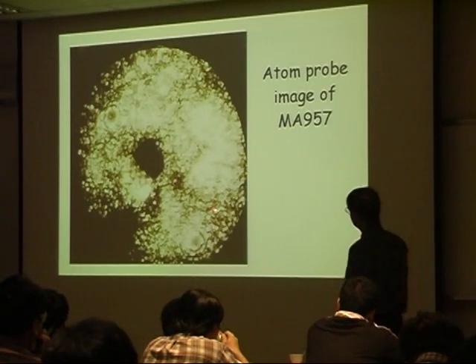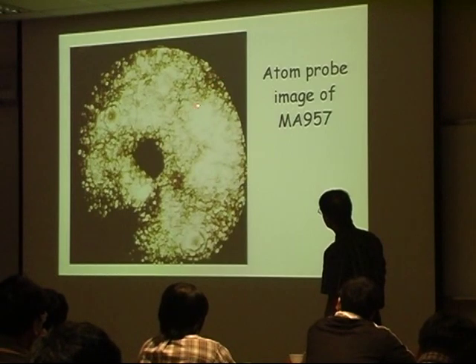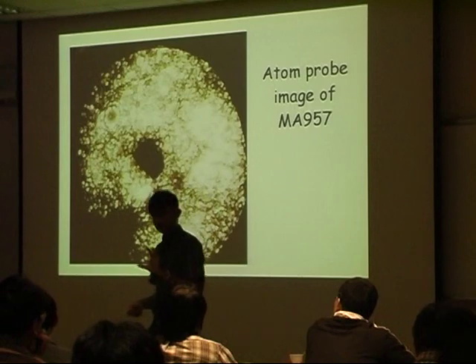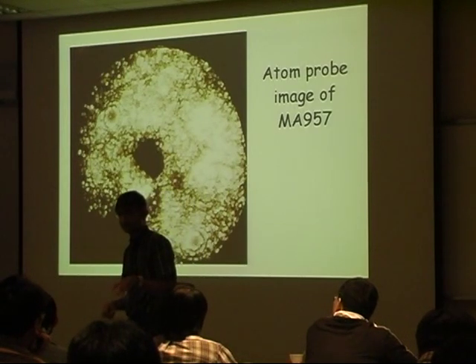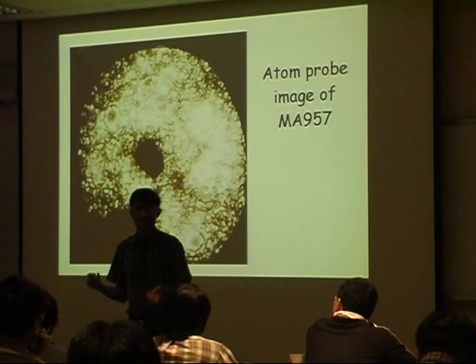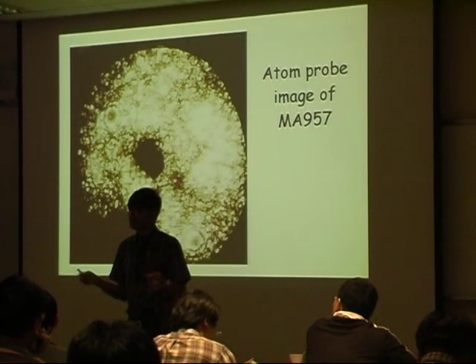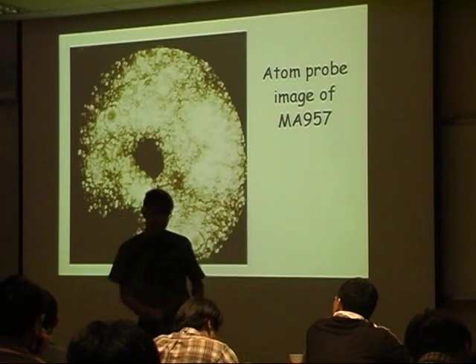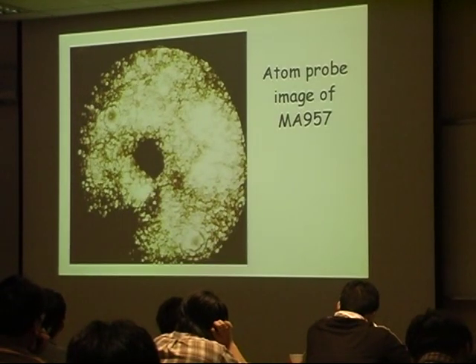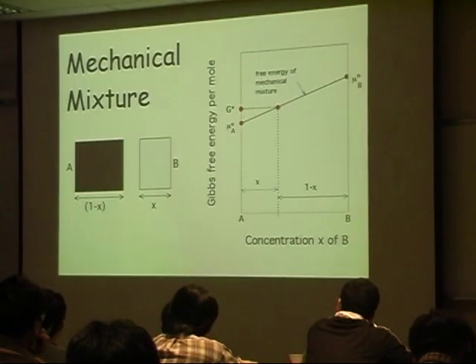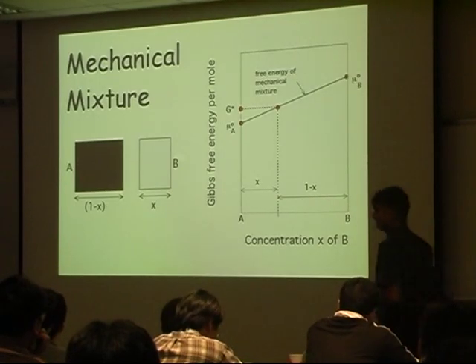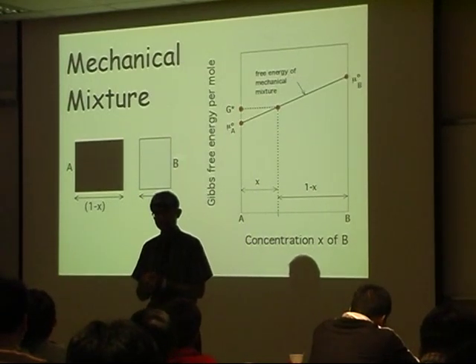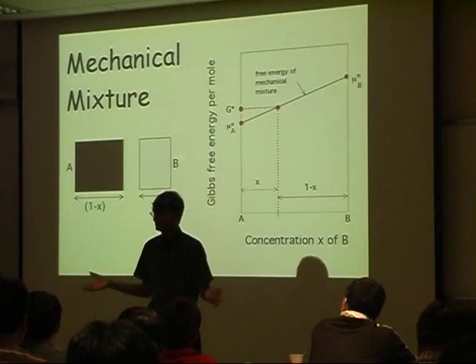What this means is that the mechanical alloying process has sufficiently severe deformation to produce a true solution. Those variations you see are simply statistical variations because we are looking at small numbers of atoms — just like opinion polls. So the first conclusion is that we have produced a true solid solution by mechanical alloying. We also produce an incredibly fine grain size, which is not very surprising because the strain involved is enormous.